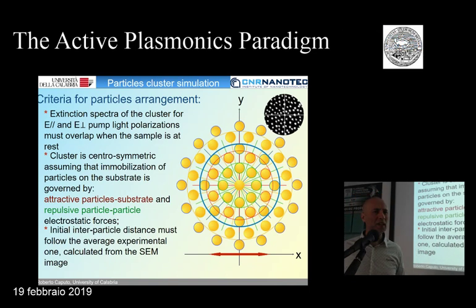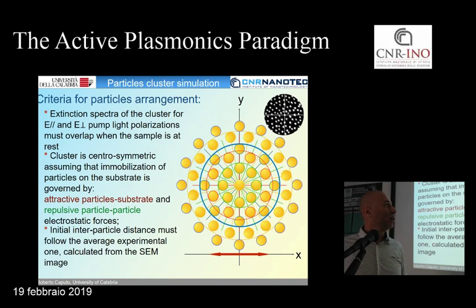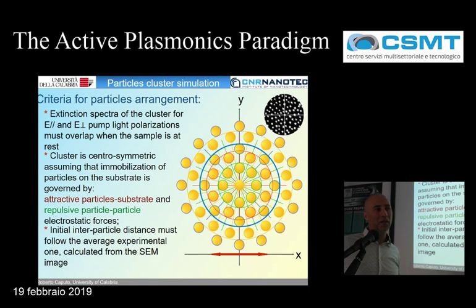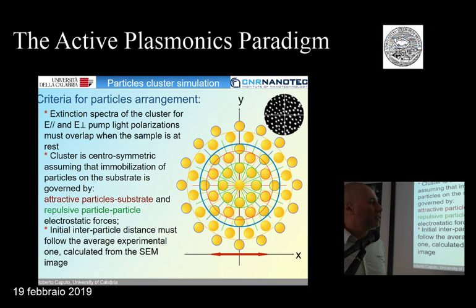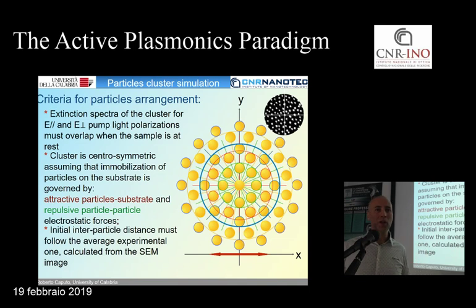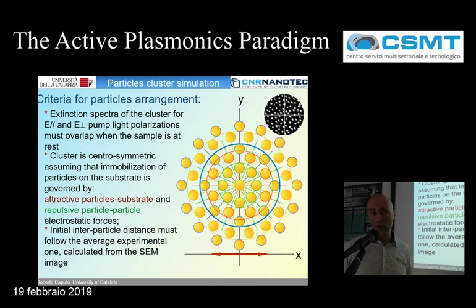So we started considering this kind of cluster of particles, which is in some way similar to the real one if you have a look at this part of this SEM picture. But in principle, we tried to keep some conditions which could give some reliability to our results. So in particular, the point is that without stretching, you need to have the same spectra if you consider this or this polarization, so vertical or horizontal polarization. And this is true in this case because the sample is just centrally symmetric.